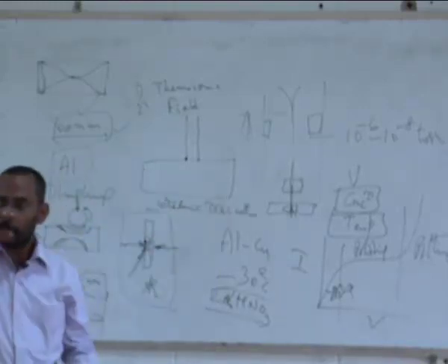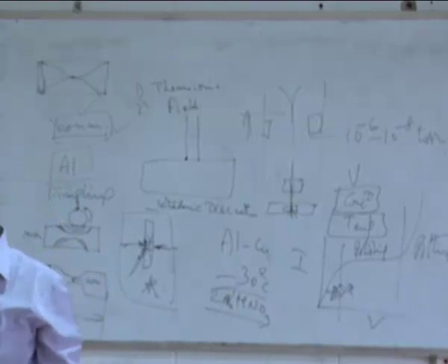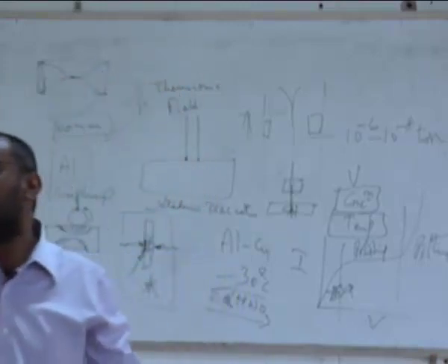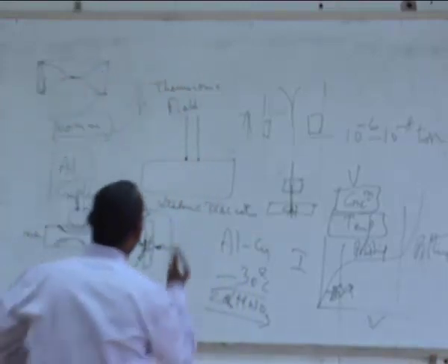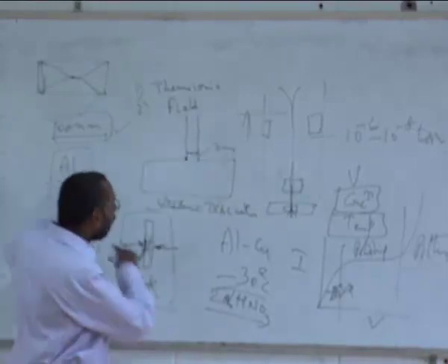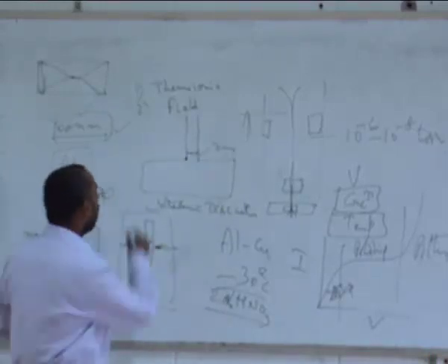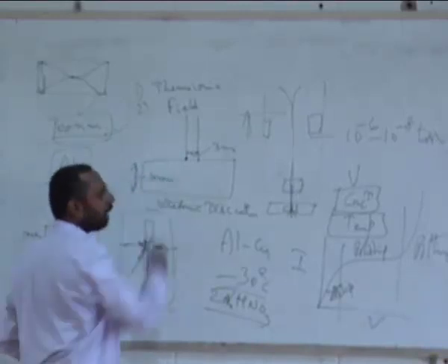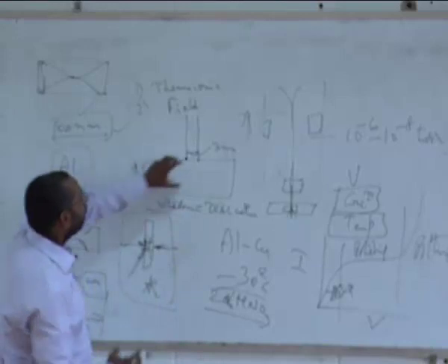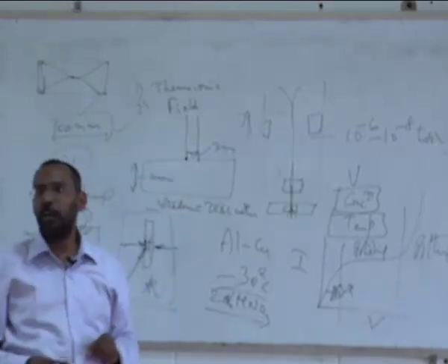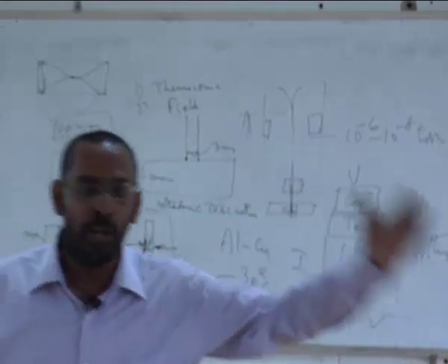By ultrasonic vibrations, it penetrates through the sample and keeps on rotating so that it scoops out a 3 millimeter disc, because the diameter here is 3 millimeters. I have already sliced my sample and maintained the thickness at 100 microns. So now I have a 3 millimeter round pellet with a thickness of 100 microns. Then I start from there and do dimpling and then ion milling, and finally the sample is ready.